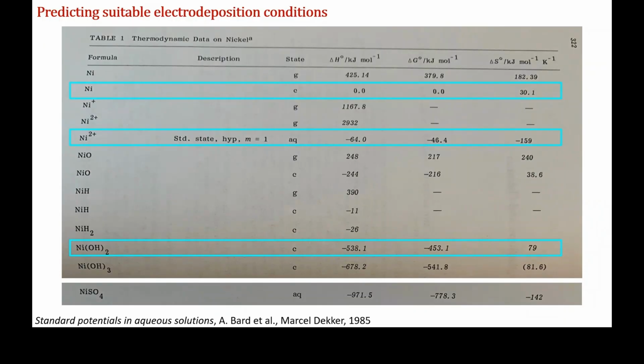And also, if you look further down the page, let's say you've added nickel in the form of a nickel sulfate, you might find that there is an aqueous nickel sulfate species. Which means that even if you added nickel sulfate as a solid, and you've seen your solution turn green and you're like, well, that's fully dissolved, it doesn't mean that there is no aqueous complex between the nickel and the salt that it just came from. And we can't know in advance whether, in the solution that we've just made, we are going to have nickel 2+, more aqueous nickel sulfate, or whether it is all going to be nickel hydroxide. How do we know? So that's the question.